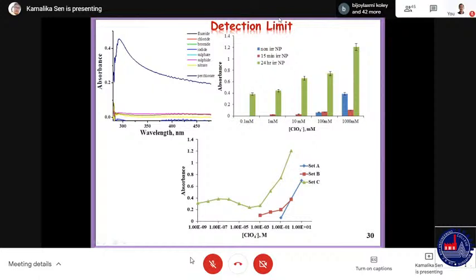And for the non-irradiated nanoparticle, the blue one, the absorbance value increases at higher concentrations of the perchlorate, 100 millimolar, 1000 millimolar. For the 15 minute irradiated nanoparticle, it increases at a little bit lower concentration, but with the 24-hour irradiated nanoparticle, it starts at a very low concentration of perchlorate, and the sensing ability starts with a very low detection limit, and the linearity is also good for set C, as we can see here.